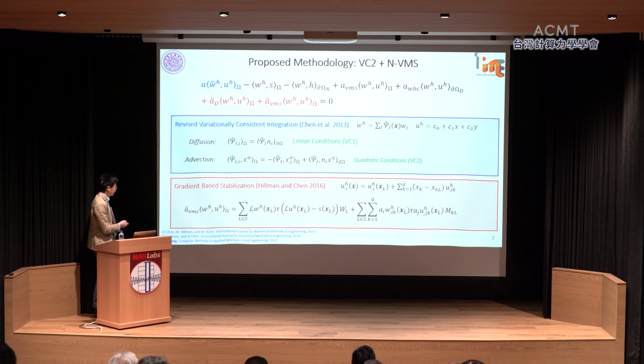The second enhancement you can do is by using the gradient type stabilization by introducing the high order Taylor expansion on the test function and trial function. And the key of what I did here is to introduce that to the VMS term, the variational multiscale term, instead of the advection term, because first you will violate the VC2 condition if you simply do a straightforward Taylor expansion. The second thing is the advection term is a non-self-adjoint operator, and the high order terms put on it, you can imagine it's more like enhanced integration, and that will actually show a little bit more oscillation from the numerical observation or in our internal testing. So we actually do that for the VMS term to obtain more stabilization. And for the details, you can check my recently published CMAME paper.